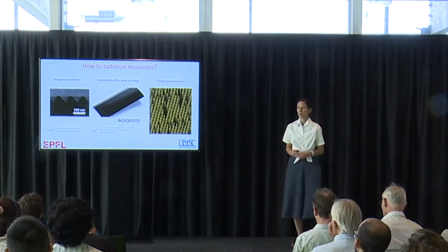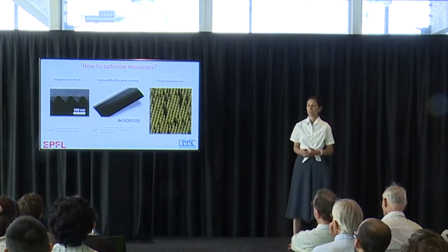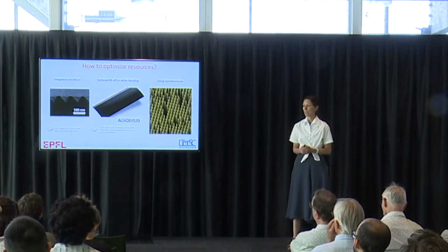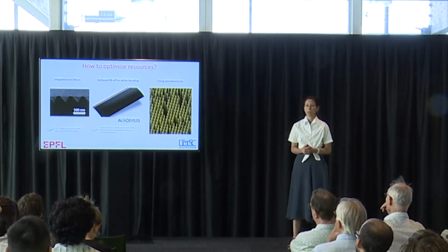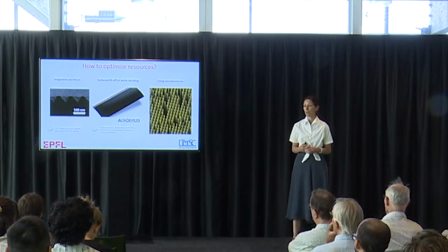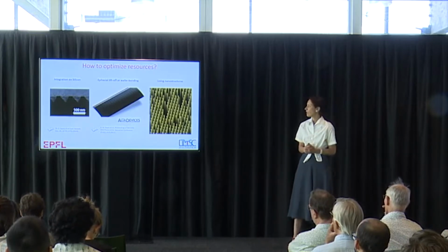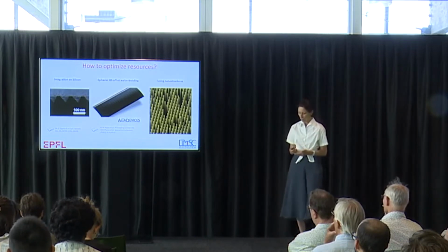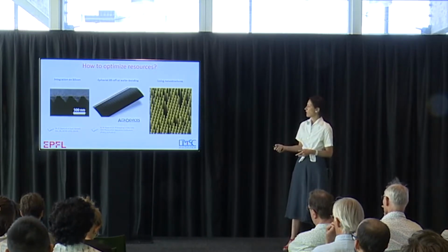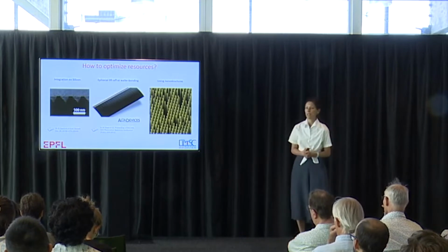How do people do this? Some people have different strategies. One strategy is we continue using gallium arsenide, but we just use less of it. It is a reasonable hypothesis. With this you can reduce the usage by about 1,000 times. And there are different strategies that people use. Some people try to get high quality gallium arsenide on silicon. This is the work, for example, on the left.